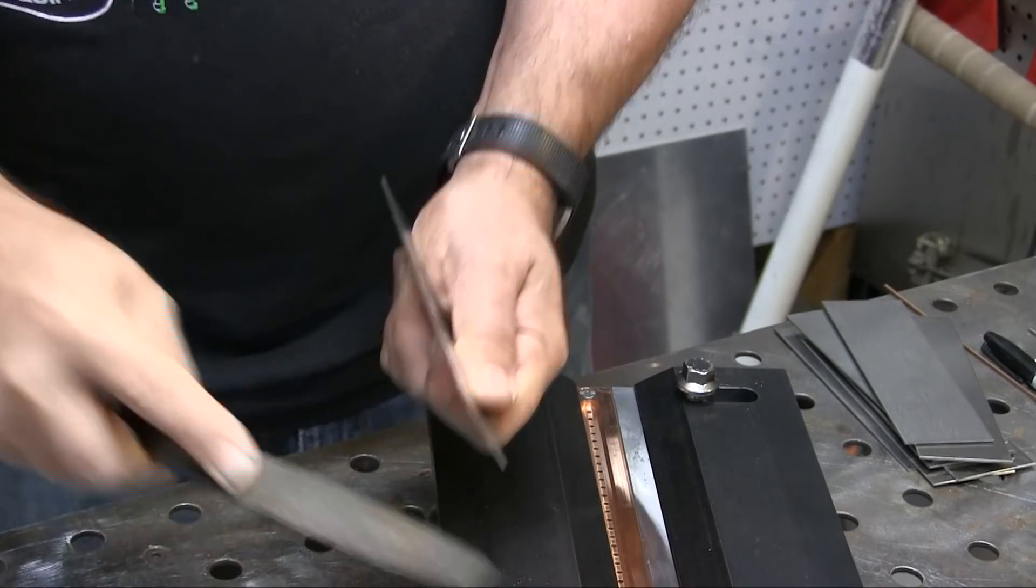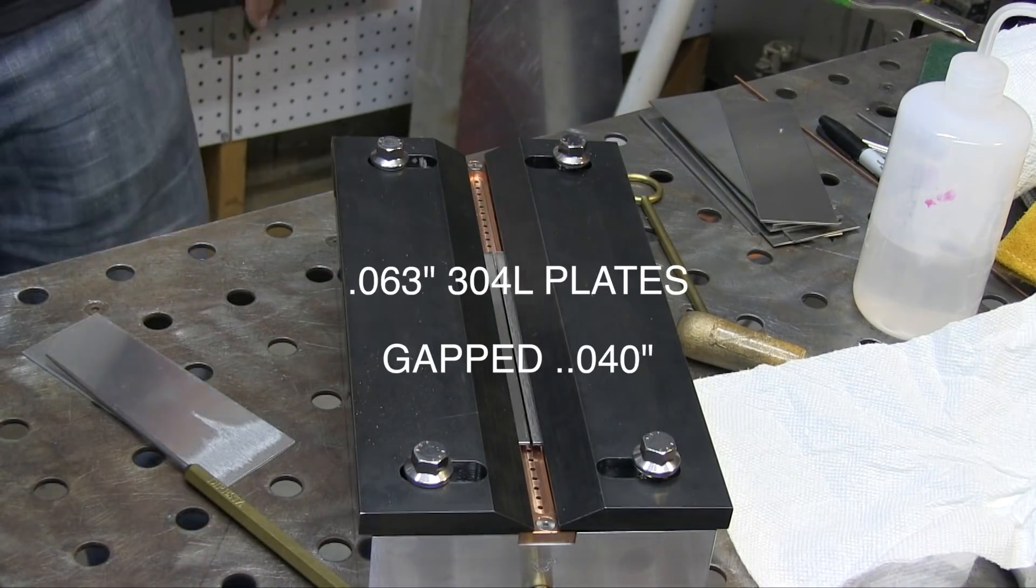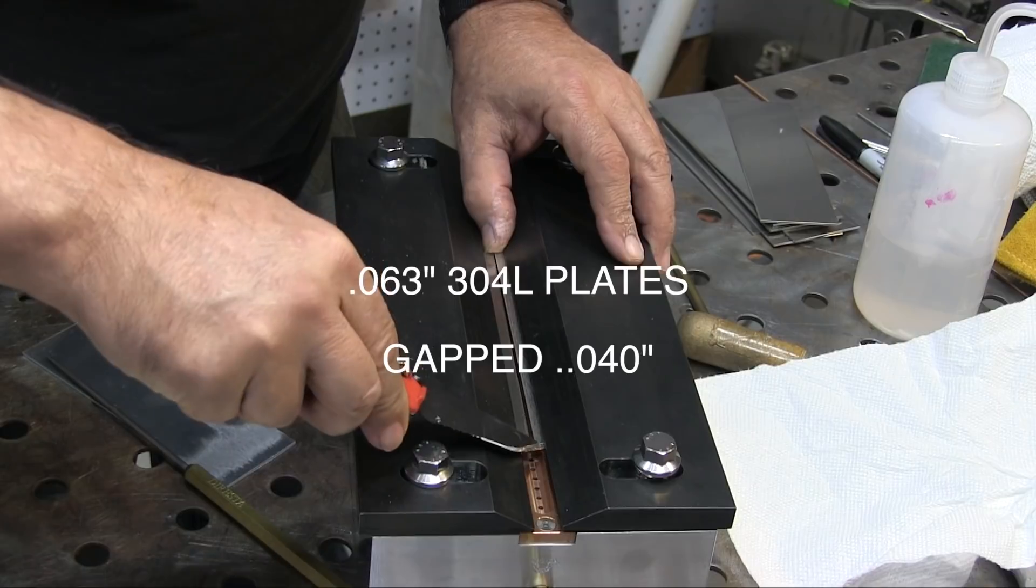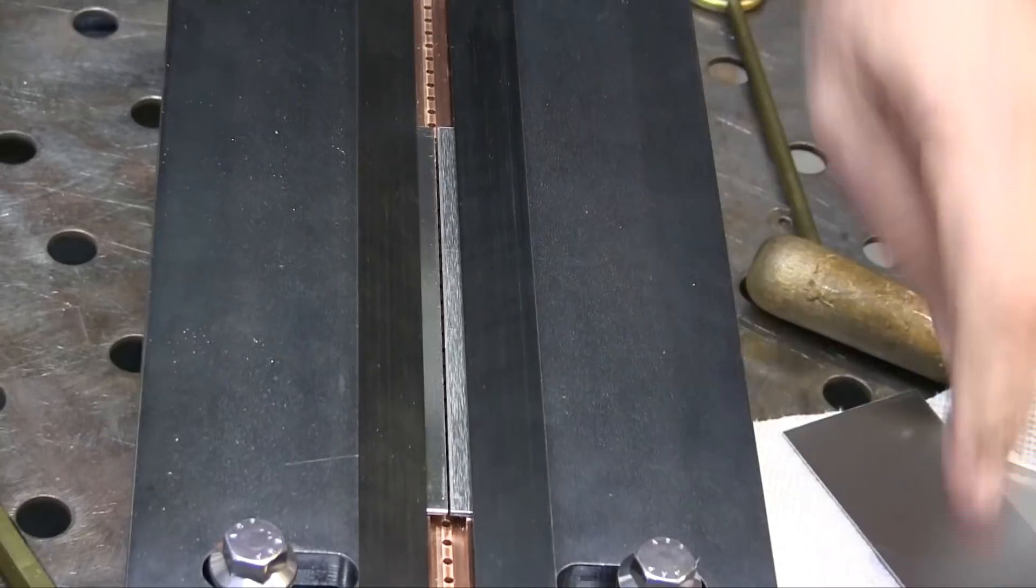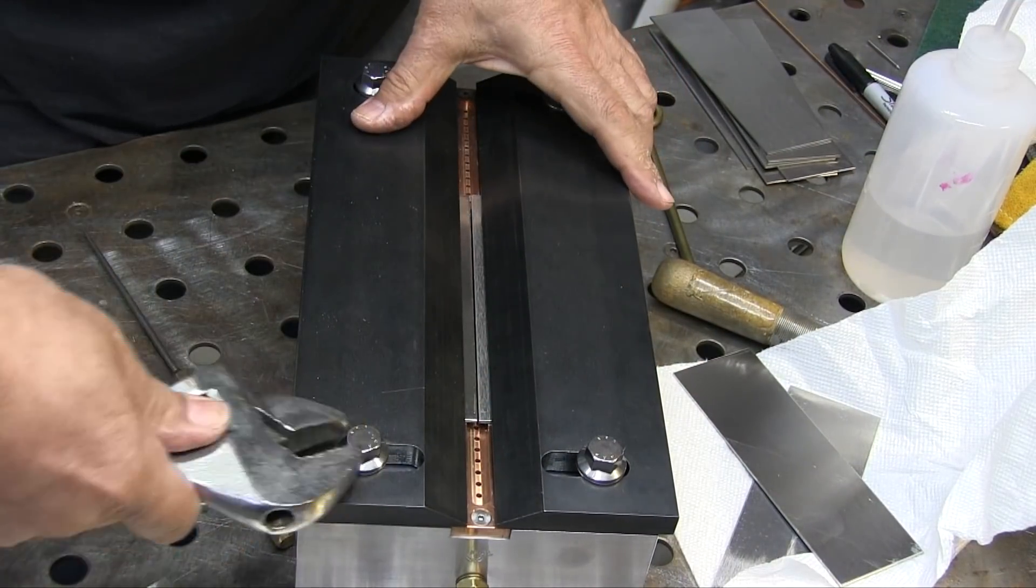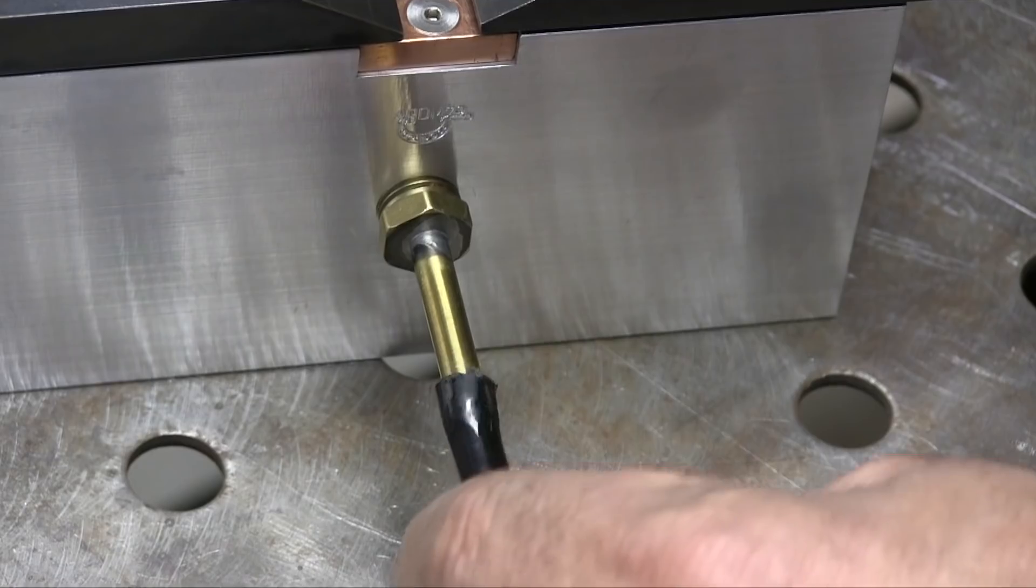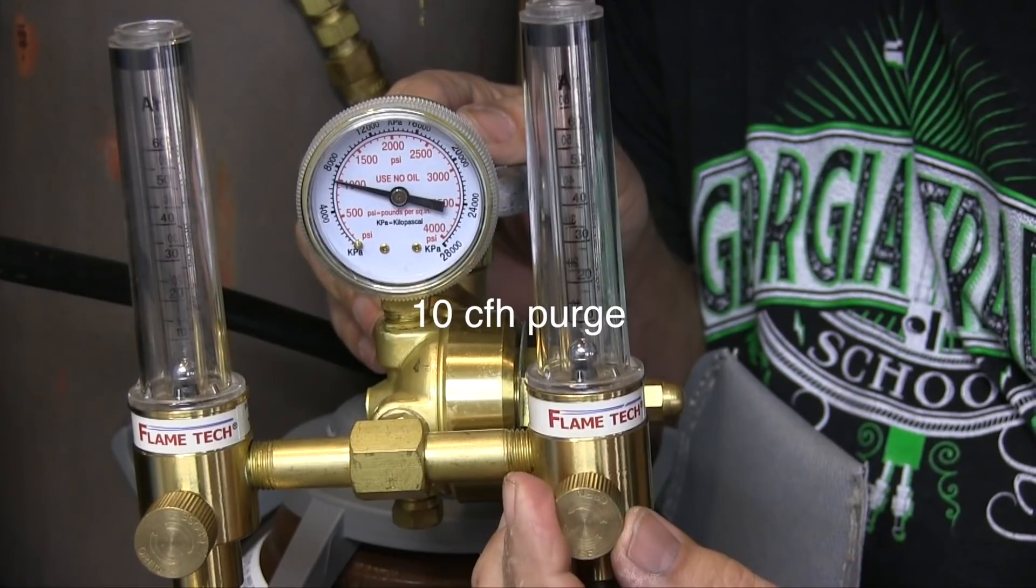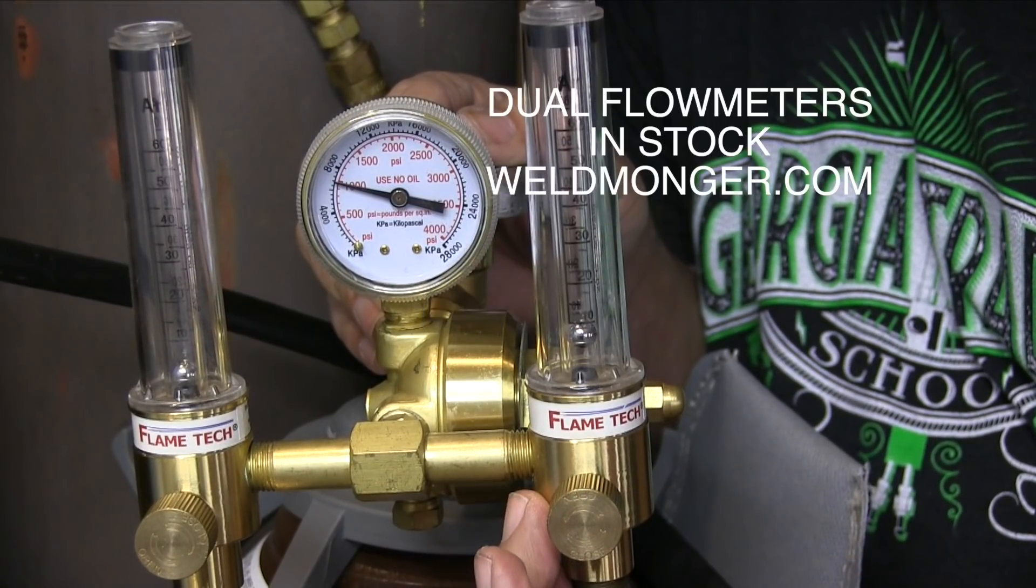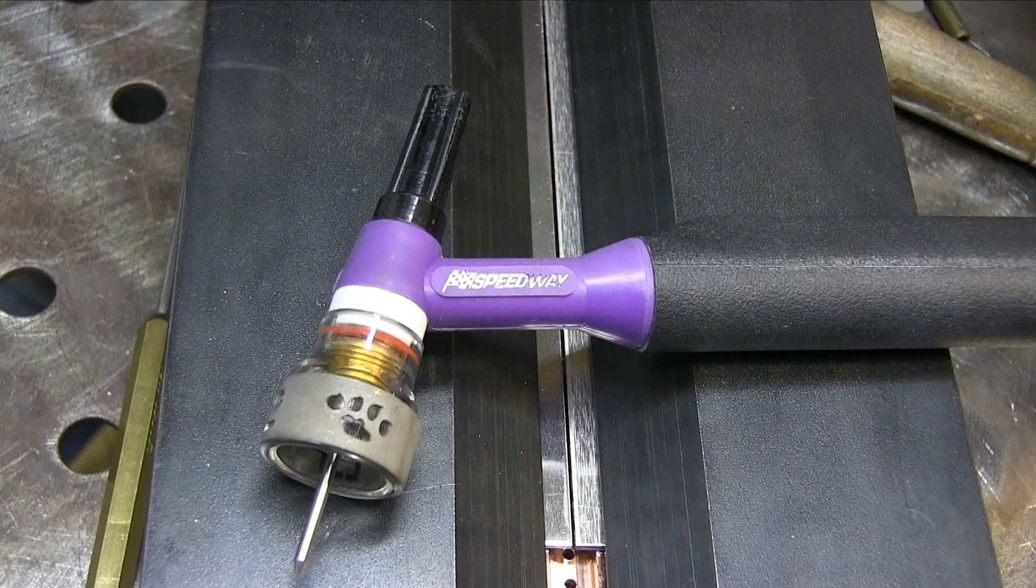One of the most important things is filing an edge on a joint like this. It's best to use a clean new file followed by an acetone wipe. Sometimes you might use a fine abrasive to knock down an oxide layer. Depends on the alloy. This is just 304L stainless. Doesn't really require anything other than a filing and a wiping. It would be rare to weld this alloy for a test. Mostly it would be something like 321, 17-7. I've got a whole article on the page on my website that explains a lot of the process for testing. 10 CFH on the fixture.